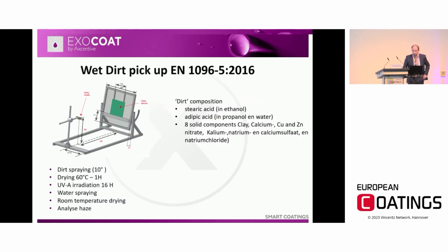Yet another test to follow for dirt pickup is this EN1096, a test developed by the glass industry. Here the dirt is a combination of organic and inorganic matter. The organic part is stearic acid and adipic acid, combined with inorganic parts based on clay, calcium, and all kinds of salts. So in this test, you spray the dirt on the glass plate. You let it dry for 1 hour at 60 degrees. You irradiate it with UV. You water spray it, dry it, and then you analyze the haze.